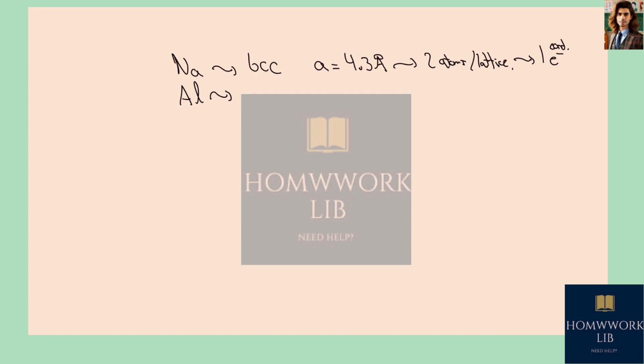Now, for the case of aluminum, it is going to be an FCC structure. The lattice constant is going to be 4.0 angstroms. So this implies that we're going to have 4 aluminum atoms per lattice. And aluminum is a trivalent compound, so each of the atoms is going to have 3 electrons in the conduction band. Okay? So this means that n is going to be the number.